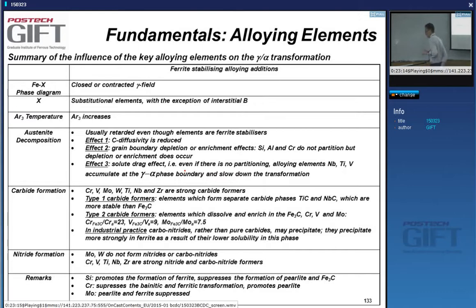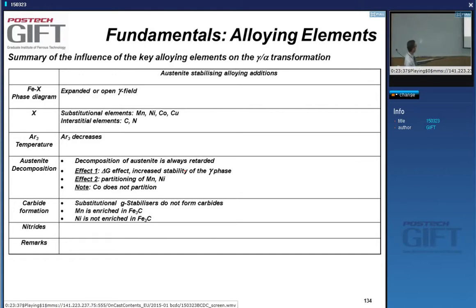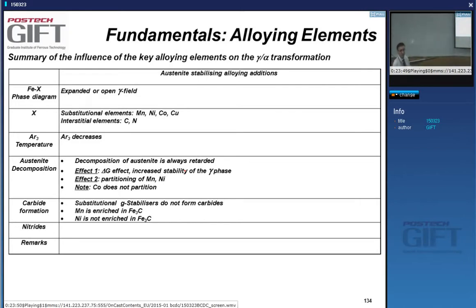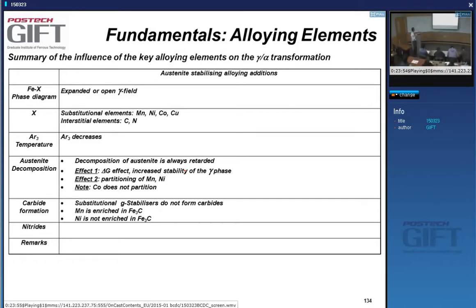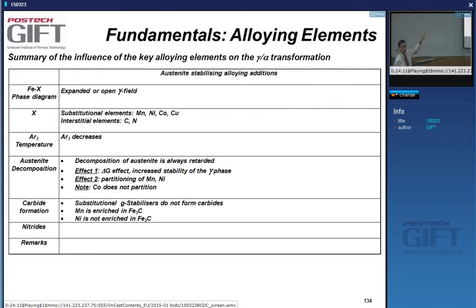Austenite stabilizers are less commonly used in carbon steels. They expand the austenite field and are usually substitutional elements. Manganese is the main one; nickel, cobalt, and copper are used less often — mainly manganese, and to a much smaller extent nickel and cobalt for special applications. Carbon and nitrogen are also austenite stabilizers. The AR3 temperature decreases as these are added. The austenite decomposition is always retarded because the austenite is stabilized — there is a free energy effect.